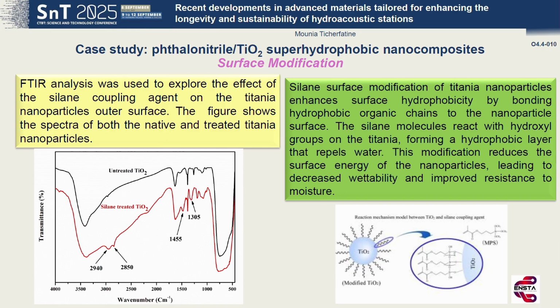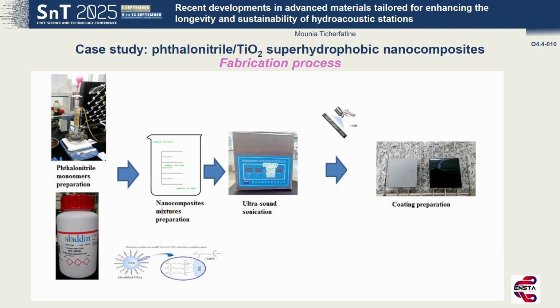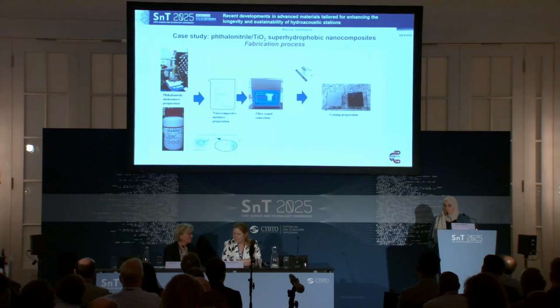Nanocomposites were prepared by adding... So prior to nanocomposite preparation, a chemical surface modification is applied to these TiO2 nanoparticles. And then the nanocomposites were prepared by adding the necessary amount of the treated nanofillers, ranging from 2 to 6% with an increment of 2% into a glass vessel containing a dissolved phthalonitrile resin. The selected substrate used to assess the corrosion protective properties was a carbon steel panel. The deposition of the nanocomposite mixture was performed by spray coating process, and the final thickness was about 120 micrometers.